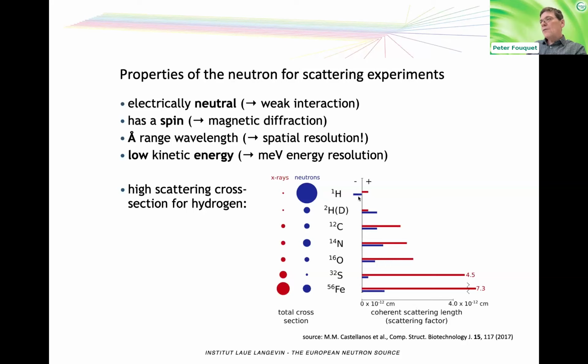And this means that if you have the right mixture of hydrogen and deuterium, which is the variant of hydrogen with 1 neutron more, then you can reduce contrast, or you can pronounce certain parts of a hydrogenous sample, and change contrast in your sample and make some parts of, for example, polymer assemblies visible and others disappear. It's used in this research, for example, with small angle scattering that Sarah showed.